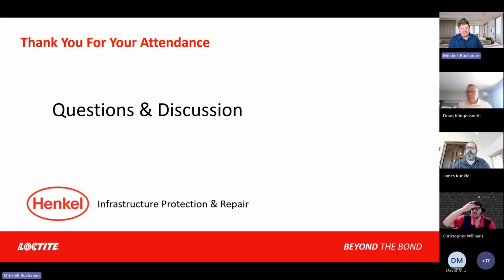Yep, biggest mistake. And Jim's probably seen this a lot in the pipeline industry, right? We see it with Mosscoat, we see it with the high temperature coatings, is really not taking the time to measure the temperature of your asset. Like a boiler, piping, you might run a high oil system at 350. Well, you put Mosscoat on there, you don't address the steam, and now it's running at 450, and you have a failure.